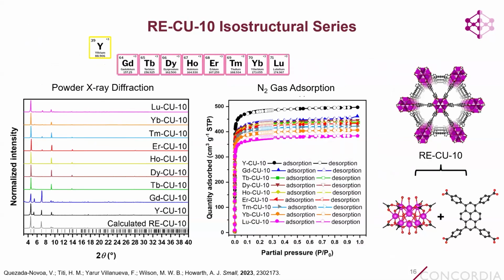And so the first thing we had to do, of course, was make all these different analogs of rare earth Cu10. And so Victor was able to do that. And these are the powder X-ray diffraction patterns showing that all the MOFs are isostructural. We were also able to determine the structure of all of these materials through single crystal X-ray diffraction. So Victor was able to make those large, beautiful single crystals for every single analog of this MOF. And they're also permanently porous with surface areas ranging from about 1,500 to 1,900 meters squared per gram.